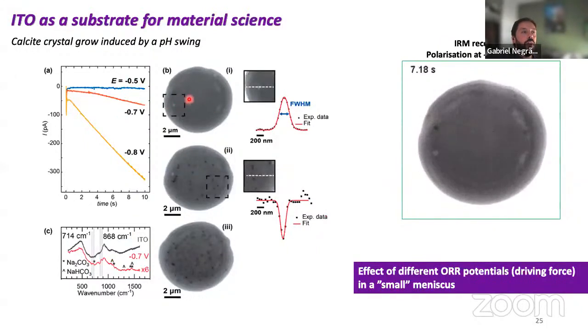So if I'm very mild here, at minus 0.5, I'll barely see something that's very, very small. If I go a little bit harder on the driving force, I see more nanoparticles. And if I go really, really harder, I see much more. And because we're still far away from the limit that we impose at -1.2 for the ITO reduction, we're seeing that this is most likely crystals and not ITO, although it's hard to be sure. We did some Raman too, and we do have the characteristics of what's expected from the calcium carbonate deposits.